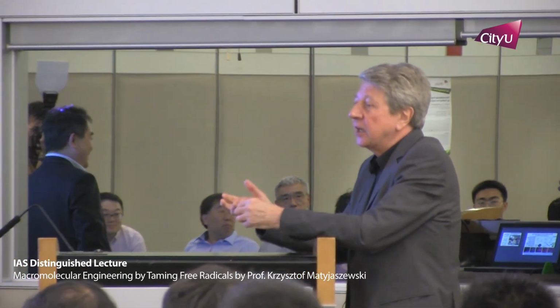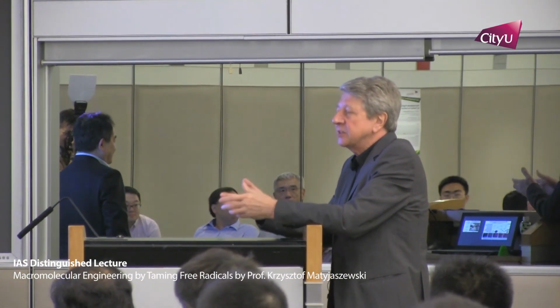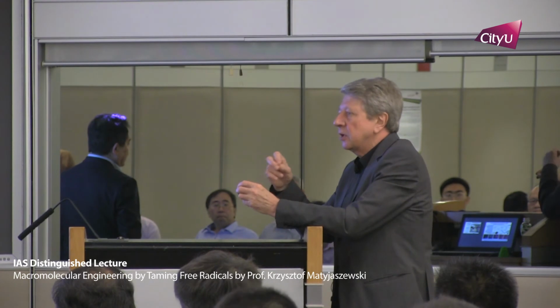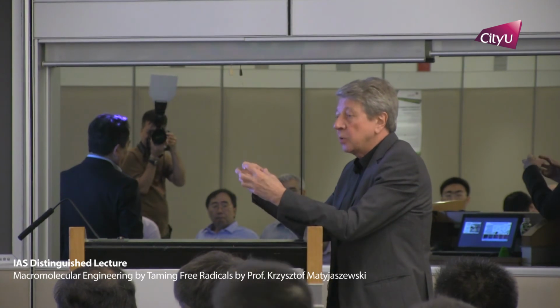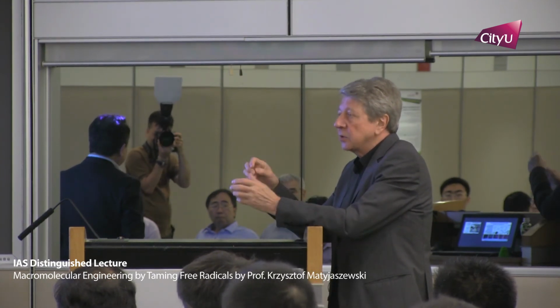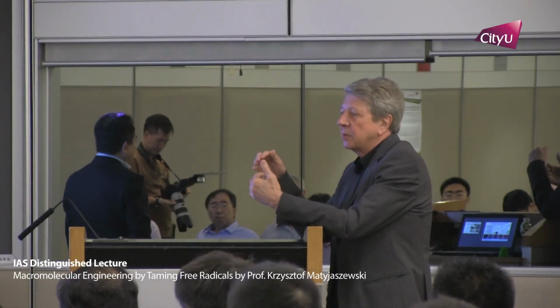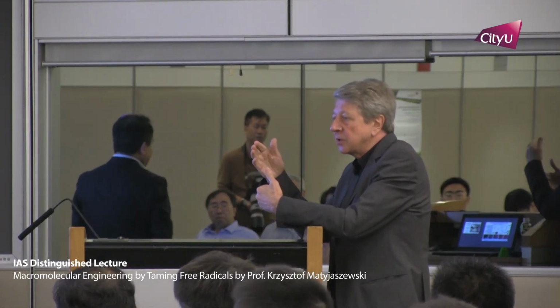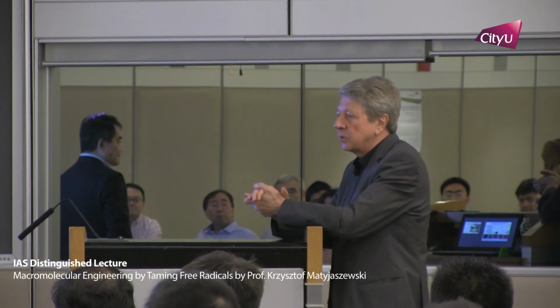I think that these reactions rely on vinyl monomers. So we must have a vinyl functionality, typically styrene, but also acrylate or methacrylate or acrylonitrile. So it means that we cannot have any kind of highly conjugated systems in a main chain, but we can have them in a side chain. So if you would really immobilize some optoelectronic materials or attach them to the acrylate or methacrylate functionality, you can potentially polymerize a backbone, and then you will have these side chains of corresponding properties.